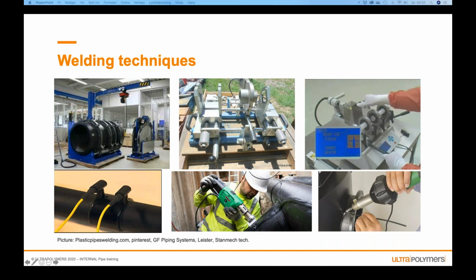Here we have extruder welding, which is pushing polyethylene through the extruder, heating it up, and then pushing it along the place you want to weld. And this is the same, but instead of an extruder, you're only using hot air, and you're manually feeding the welding rod.